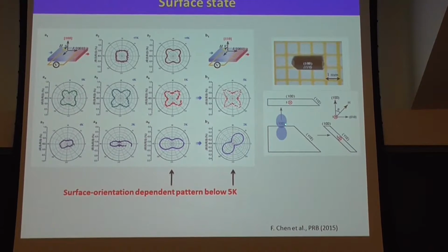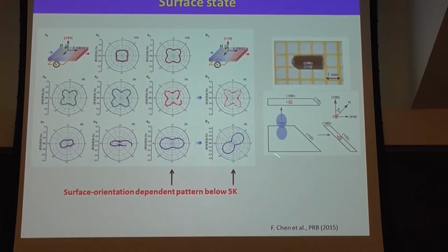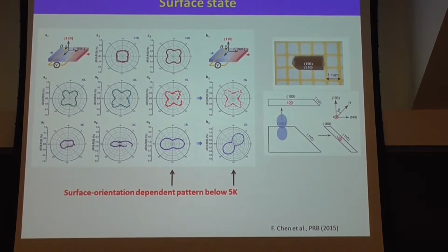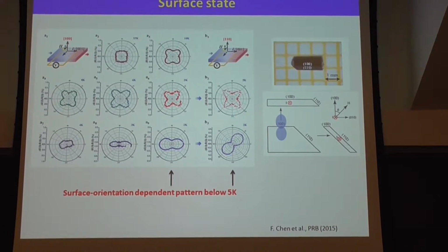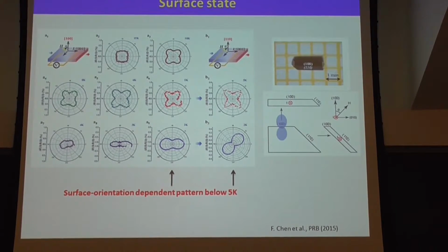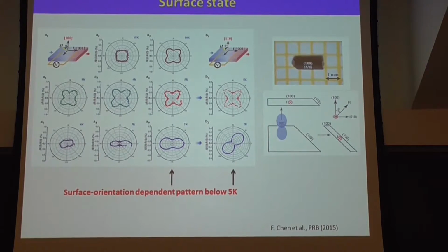it is due to the surface, you know. Because the surface is here and you are rotating here, the surface always stays in the plane. This means when you rotate the field, it is always twofold. But above that, the surface state, because the fourfold is due to the structure, this is a cubic structure. Of course it's fourfold symmetry, right?